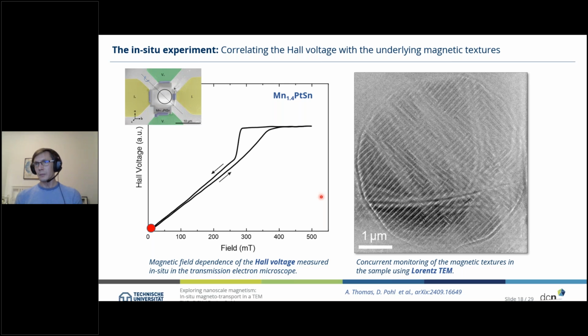So you see we have different contrasts here in the Lorentz TEM images. We have some stripes either in this direction or perpendicular. Since it's a single crystal, we see some bending contours popping up in the image as well. If I now run the video again, increasing the magnetic field value, we will see that the spacing of these stripe patterns will increase. Just before saturation, we will see the appearance of some magnetic textures like non-topologic bubbles and anti-skyrmions.